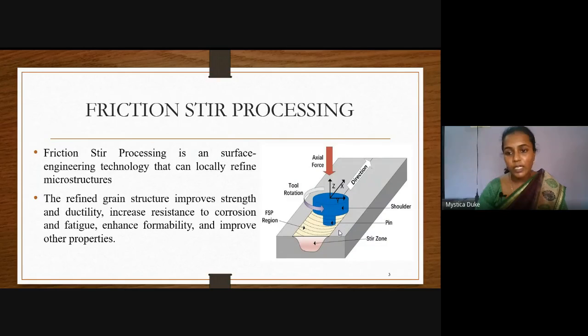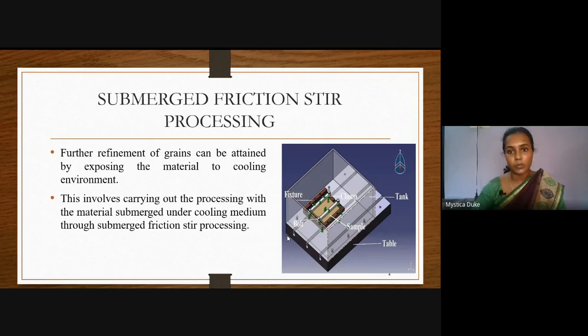So we can actually take away the heat that is coarsening the grains in this region. So when we take away the heat, we can also get finer grains in this region. That is the heat affected zone. We can reduce the size of the heat affected zone and we can actually refine the coarse grains in the heat affected zone. So this is why we are opting for submerged friction stir processing. Submerged friction stir processing is nothing but submerging the whole setup inside a tank and filling the tank with whatever medium we choose.